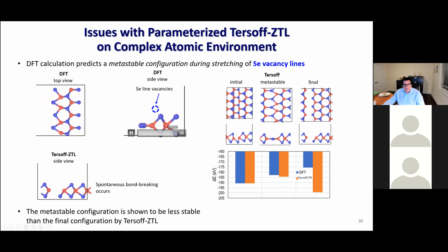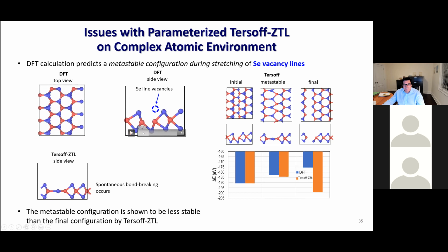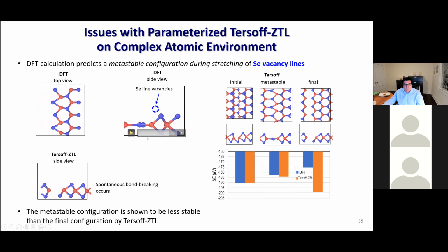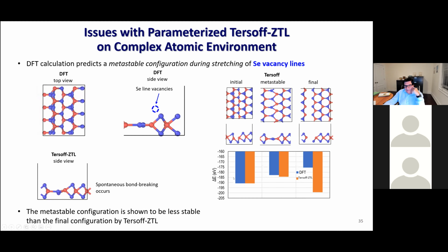What is the particular deformed shape after dissociation? It remains horizontal. However, Tersoff, after breaking, gives you a tilt of this atom, as is shown here in this movie, and that is very problematic. If you look at the energetics in the initial, metastable and final state, DFT tells you that the energies are increasing. So this is the most stable, and this is the least stable. But look at what the Tersoff does. First it goes down, but then it goes up. So it tells you this is the most negative, the most stable, which is obviously wrong.